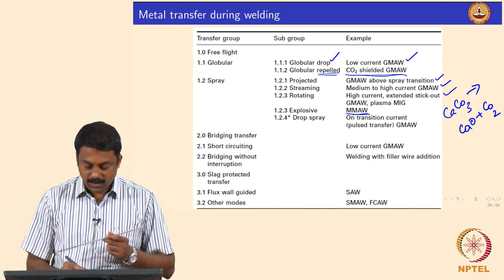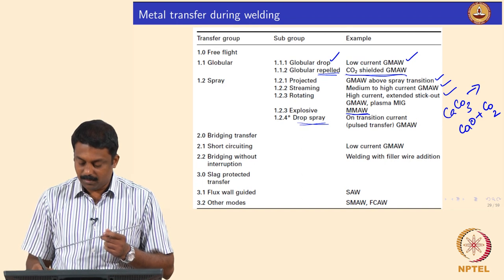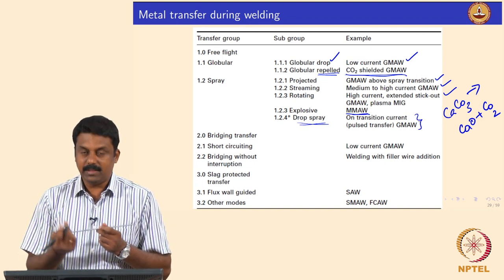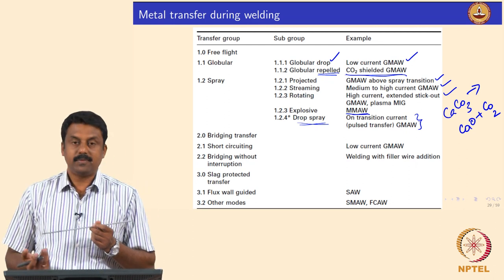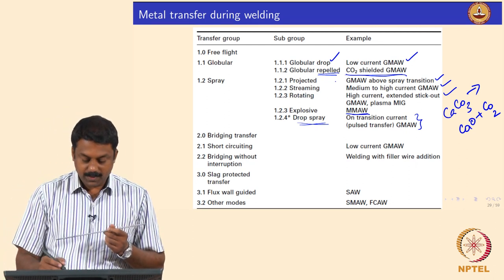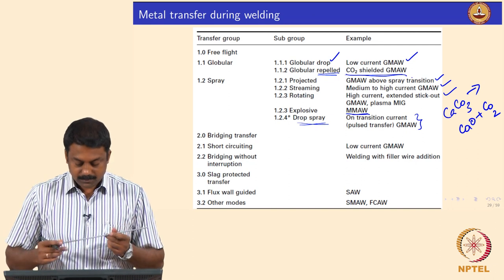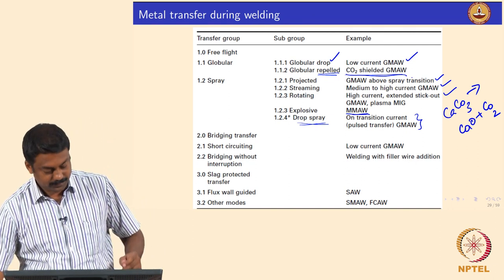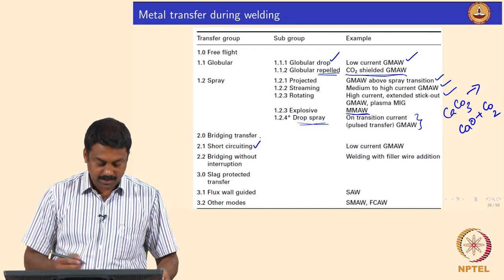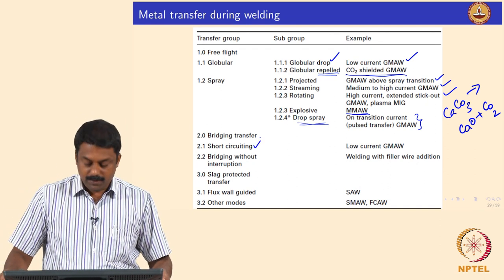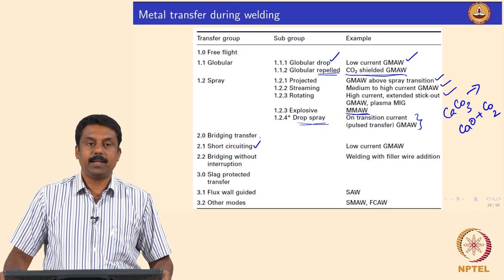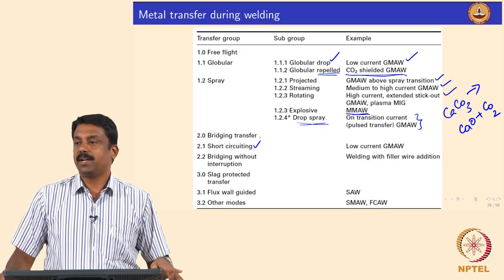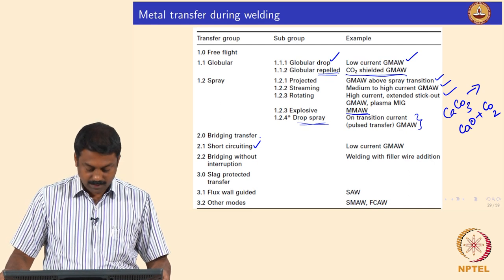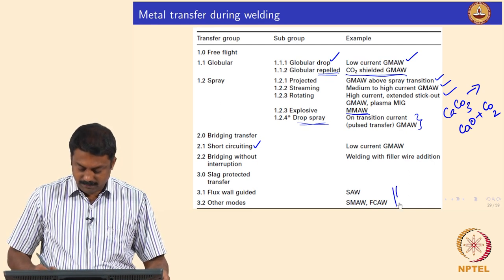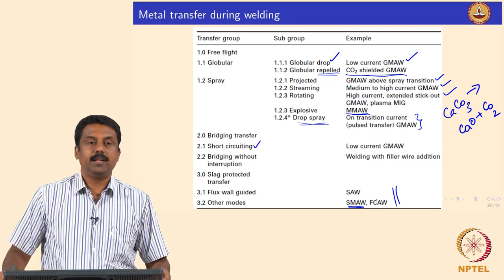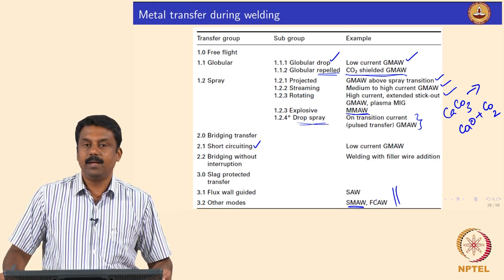So, drop spray, just above or around the spray transition, is the most advisable transfer mode, the drop spray or the projected spray. Various transfers you would see. You can also achieve the short circuiting transfer by carefully playing around with GMAW parameters like wire feed rate, voltage and current. And other modes you will see when we are looking at the mechanisms of SMAW and FCAW.